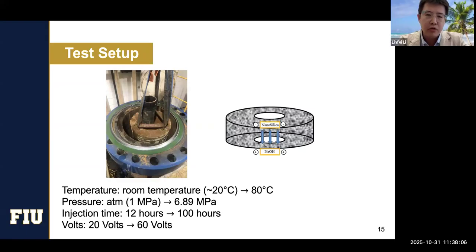To mimic the real underground environment, we boosted the temperature from room temperature, as we did for the lab scale, to 80 degrees C. We also pressurized from atmospheric pressure to 6.89 megapascal. We didn't go to the maximum because we have some safety concerns, but also because the sample is much, much larger. That's why the injection time extended from 12 hours to 100 hours, and the voltage from 20 volts to 60 volts.